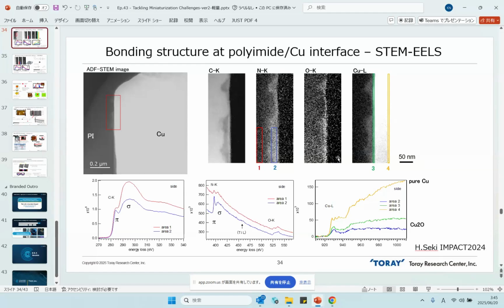Okay, so now we think the root cause of poor adhesion is diffusion of copper, because all the literature also says that by the copper diffusion from the copper oxide surface layer, a kind of void can be created at the surface of the copper. Because the copper ion diffusion velocity is much higher in the case of copper oxide compared to pure copper.